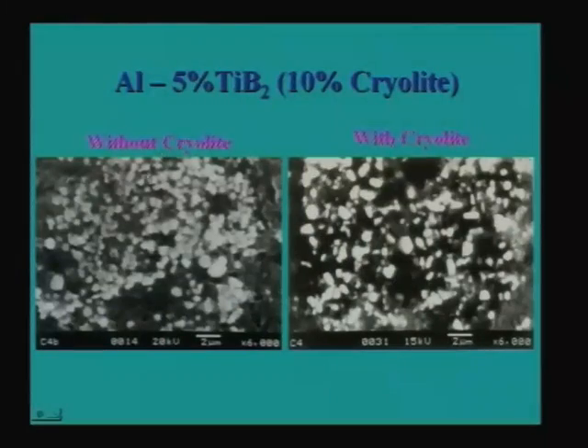So you have to control this reaction in such a way that the reactivity of both is more or less controlled. So cryolite is one such agent which we add, which can reduce the reactivity of the K2TiF6 with aluminum, so that the reaction of both occurs simultaneously. Otherwise you end up with only Al3Ti and not the TiB2. So one has to control that. People have done that in a number of cases. If you don't have cryolite addition, you get agglomeration of particles which contain both Al3Ti and TiB2, and if you add cryolite, you have more or less uniform distribution of only TiB2.